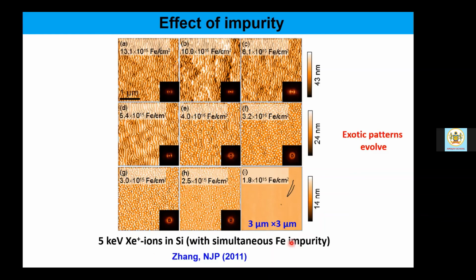And during this xenon ion bombardment, simultaneously, an iron foil was kept near the ion beam, so that it was continuously sputtering. It continuously sputtered the iron atoms, which easily got introduced into the target material. And it led to very exotic patterns, which are otherwise very difficult to form. So the take-home message is that the introduction of a second component can sometimes do havoc.